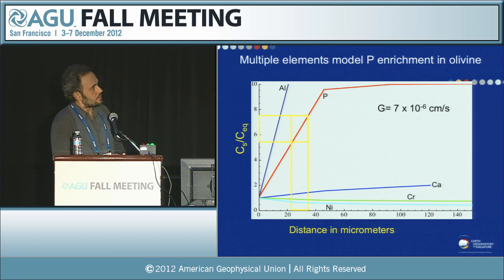Another interesting observation here: the model predicts that the aluminium would be even more enriched, and we'll come back to this. Calcium, not so much because of the partition coefficient and also the diffusivities, and nickel would be a little bit depleted.